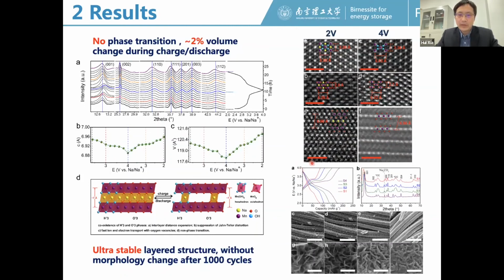Then after that, we further did the XRD and SEM for the sample, and we can find that this layered structure is well retained after thousands of cycles, and even the morphology is also well retained after the cycling. So this further demonstrates that this layered structure with large interlayer spacing is highly stable for reversible sodium intercalation and de-intercalation.